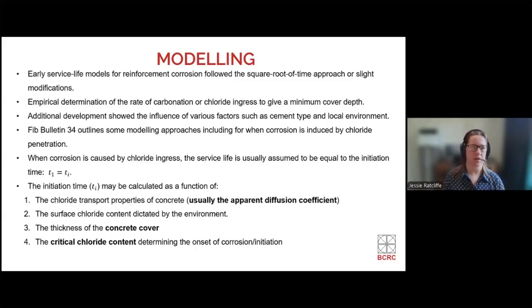One of the documents that explains these principles of service life design and calculation is the FIB Bulletin 34 model code. And this document presents strategies for service life design of concrete structures, including the concept of chloride-induced corrosion, modeled by diffusion through concrete according to Fick's second law. When the corrosion is caused by chloride ingress, the service life is usually assumed to be equal to the initiation time. So when that steel is depassivated by the chloride and corrosion can start.